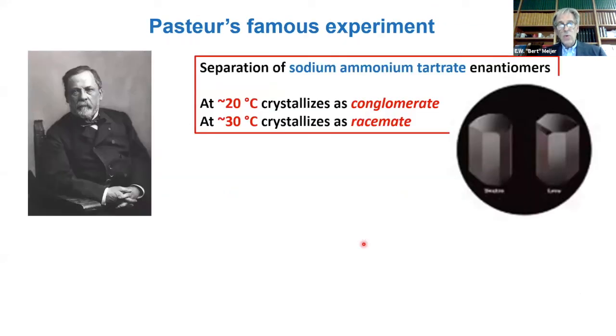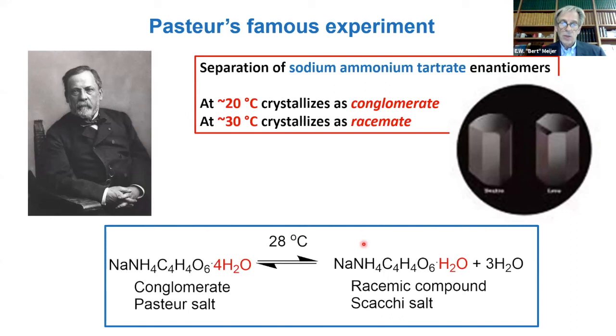I'd like to come back to two famous people, Pasteur and van 't Hoff. We all know Pasteur's famous experiment about the sodium ammonium tartrate, isn't it? He crystallizes at room temperature, you get a conglomerate that gives you the, let's say, P and M helical crystals. But if he did it at 30 degrees, he got the racemate. And only at 20 degrees, he could separate the crystals of one side and of the other. And you can't do that when it's crystallized at 30 degrees. Later, they found out that the Pasteur salt had four molecules of water in the crystal structure, while the racemic compound has only one molecule of water in the crystal, meaning that water, the solvent from which you crystallize it, actually determines the morphology of the structure.